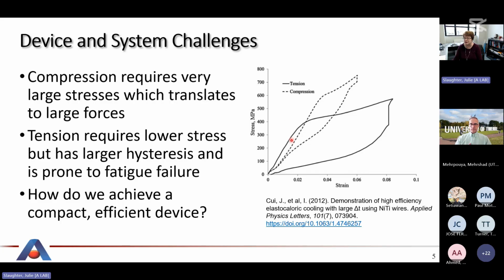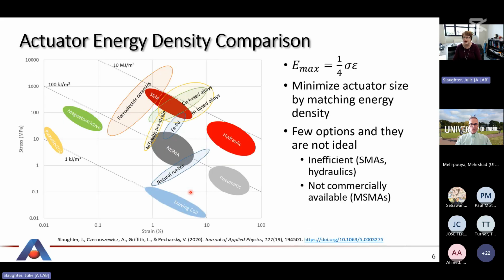This is nitinol, this is nickel titanium, which is by far the most common material used for elastocaloric systems. So in compression, it has lower hysteresis, but requires very high stresses, 700 megapascals, which is really pretty extreme. Tension needs lower stresses, but it has larger hysteresis and is prone to fatigue failure. So we're kind of looking at how do we achieve a compact, efficient device with the materials we have today. So I want to start first by talking about how do you, that big heavy piece of the system, the actuator, how do you apply the fields?